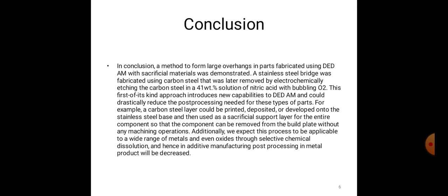Now the conclusion. A method to form a large overhang in a part fabricated using DED-AM with sacrificial material was demonstrated. A stainless steel bridge was fabricated using carbon steel that was later removed by electrochemical etching. The carbon steel is etched in a 41 weight% solution of nitric acid with bubbling O2. This first-of-its-kind approach introduced a new capability to DED additive manufacturing and could drastically reduce the post-processing needed for these types of parts in the bridge. For example, a carbon steel layer could be printed, deposited or developed onto a stainless steel base and then used as a sacrificial support layer for the entire component, so that the component can be removed from the build plate without any machining operation.